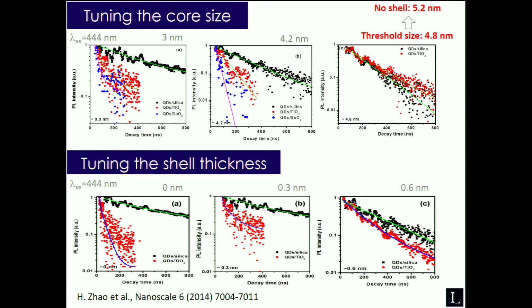And of course, if you change the size of quantum dots and increase it, you inhibit the charge injection. The same happens when you use a protecting shell, because this kind of system, especially lead sulfide ones, suffers surface oxidation. So we covered them with a few monolayers of cadmium sulfide, and as you can see here, if the shell is too thick, you inhibit the charge transfer. So it's possible to play with size and shell protection to get good electron injection from the quantum dot to the oxide.